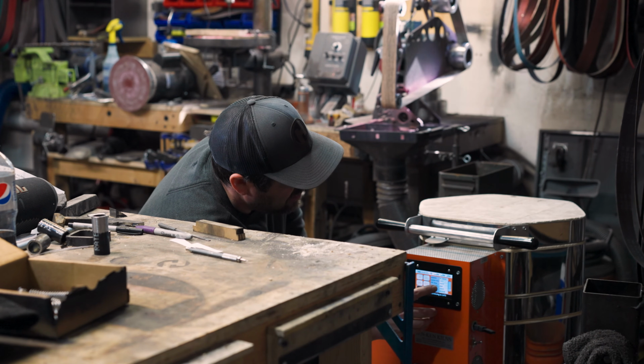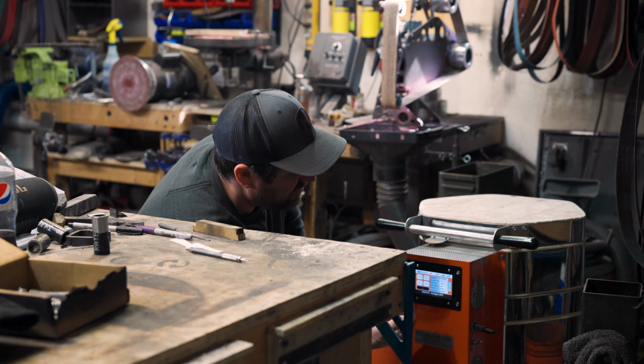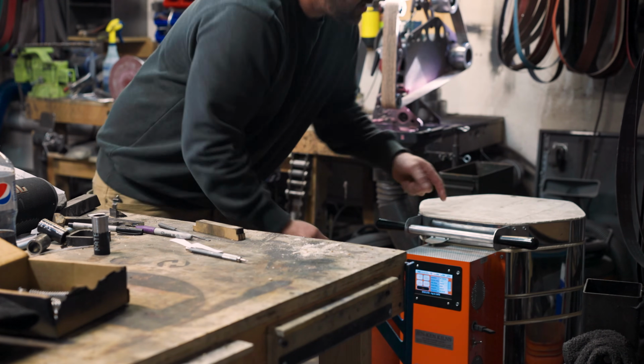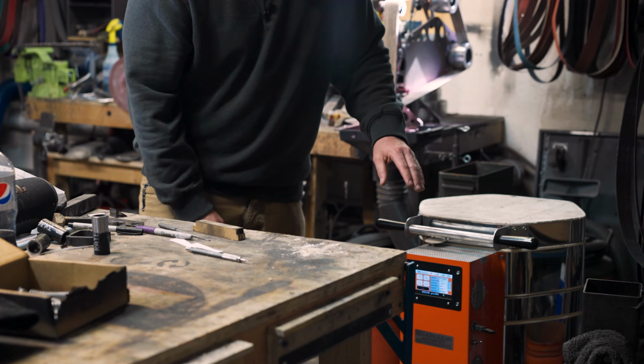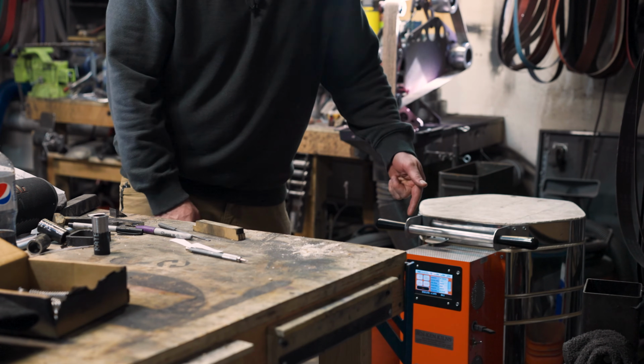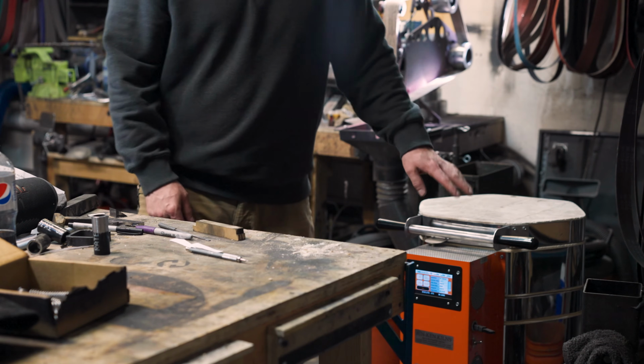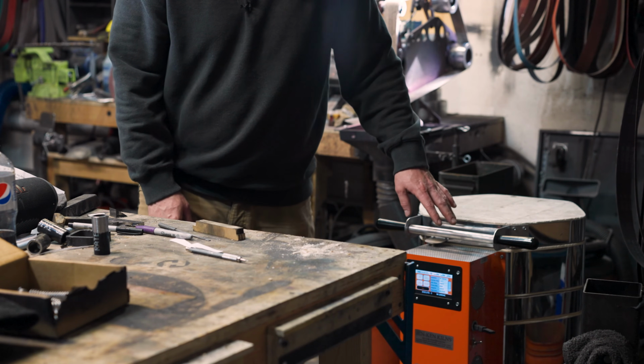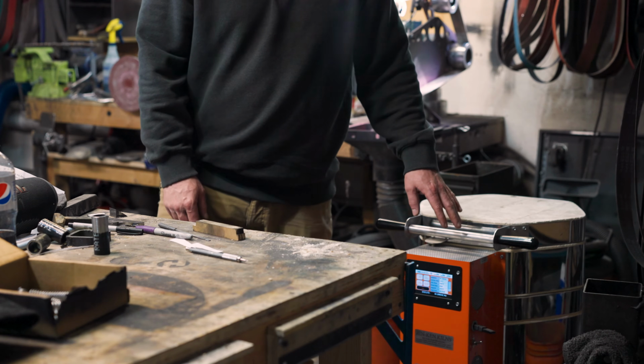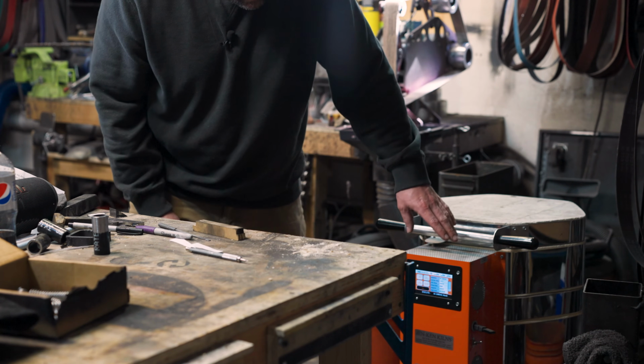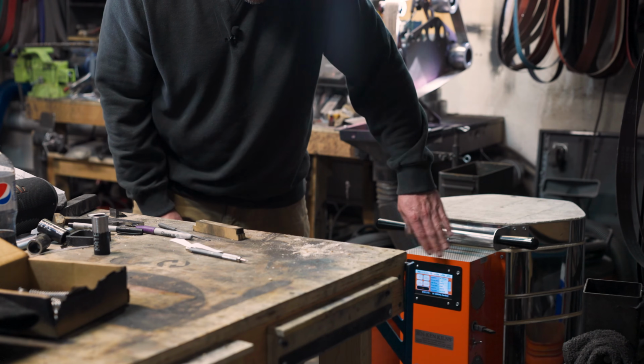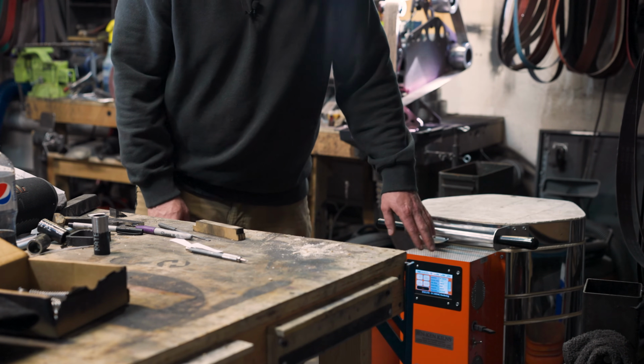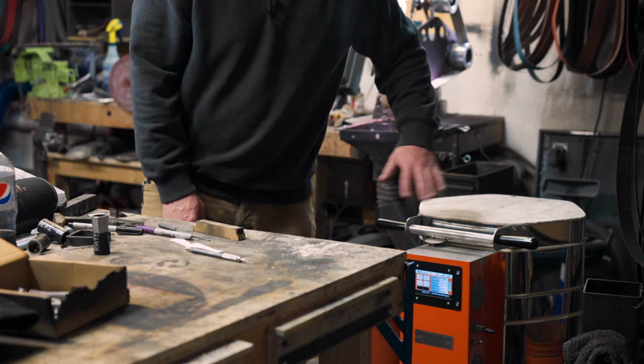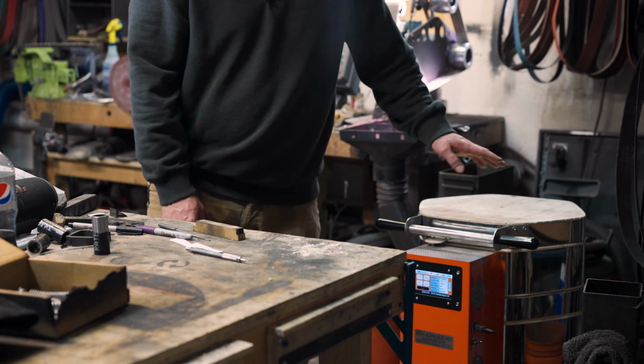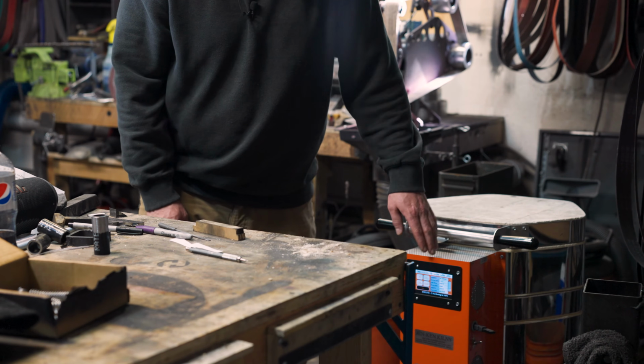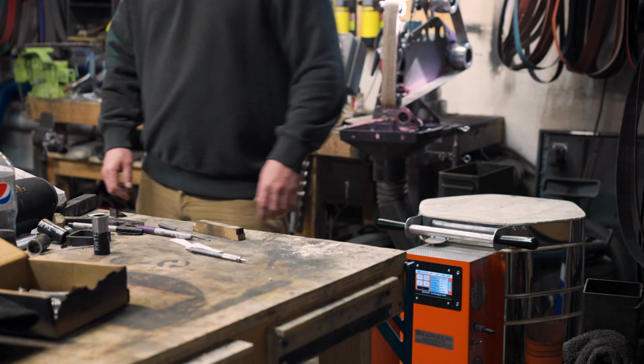So by the time this gets up to about 1400, I'm going to pop the knife back in, and then the knife is going to cool it down just a hair and slow the ramp speed. And then once we get up to our 1475, it's going to soak. I'm going to leave it in the full soak. I think it's got a 15-minute hold time on this. So we're just going to let it sit there, and because I'm not heat treating anything else, I don't need the extra time. So we're just going to let this soak to be safe and then quench it.